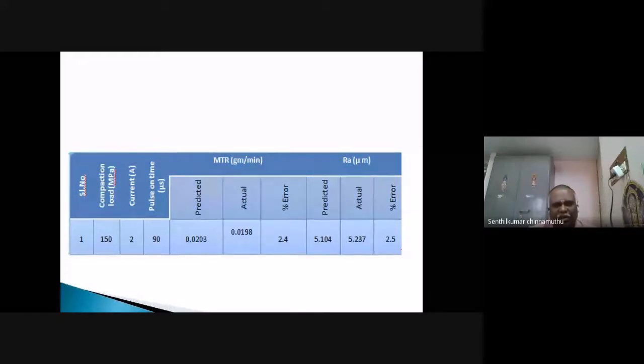With the help of this compaction load, current and pulse on time, that is the optimized values, again we have to conduct the experiment. Finally, we get 0.0198 metal transfer rate and 5.237 surface roughness. The percentage error was calculated for the metal transfer rate and the surface roughness. For metal transfer rate, the percentage error is 2.4, and for surface roughness it is 2.5,